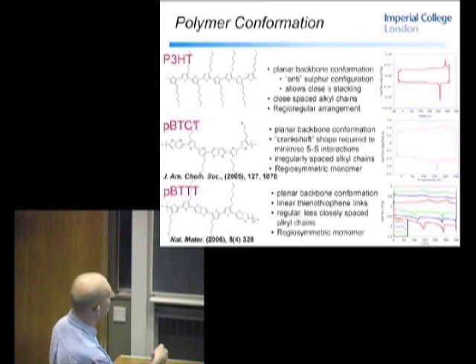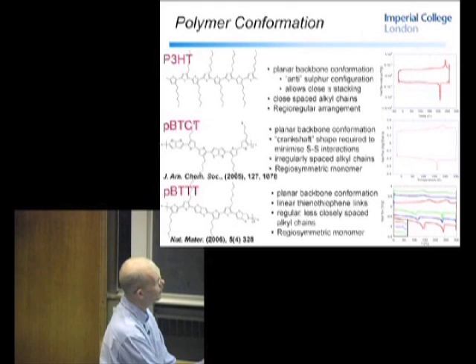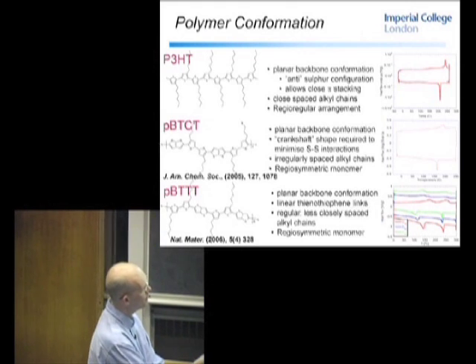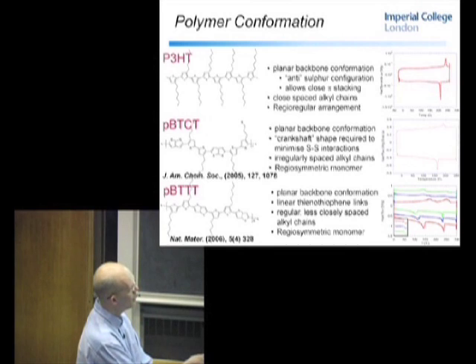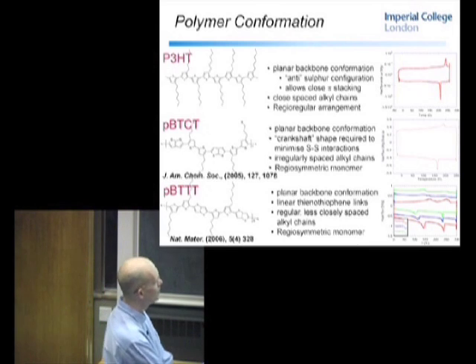In this case, in the PBTTT, because we have this regularly spaced alkyl groups and the spacing is large enough, we can get interdigitation from neighbouring units, and this gives rise to ordered side chains. In this case, it's disordered. And when we have ordered side chains, we have two thermal transitions. We have a side chain melt and a main chain melt, and we're calling the region in between these two transitions a liquid crystalline phase. It's more or less true.